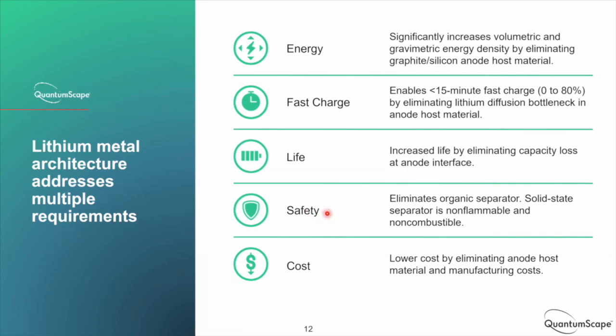Then a further benefit in safety is, if the car gets in a crash or has some over temperature event, the polymer separator can melt. And then as it peels back, it'll expose more contact area between the anode and the cathode. And that contact area can result in internal short circuits, which delivers a lot of energy to heat the battery very quickly. That is part of what can lead to this chain reaction or thermal runaway.